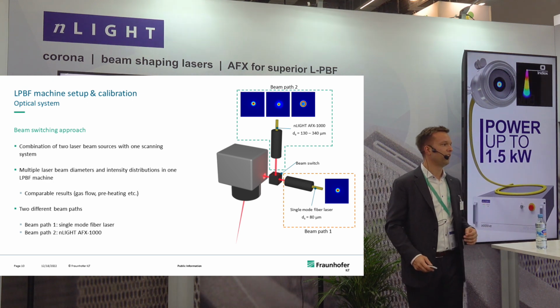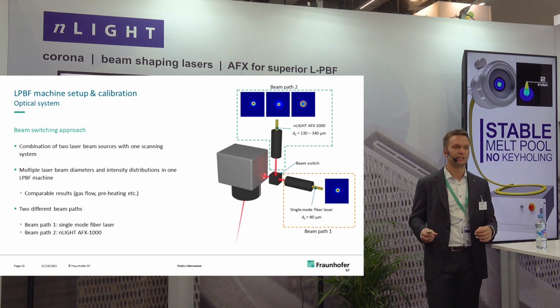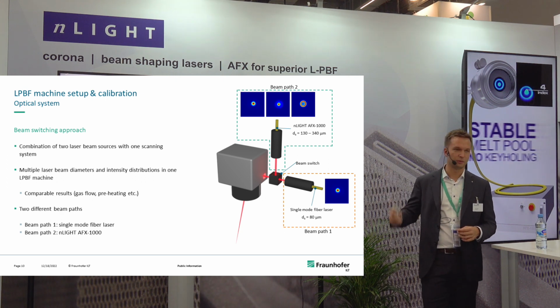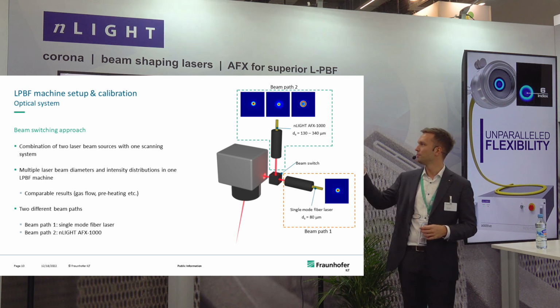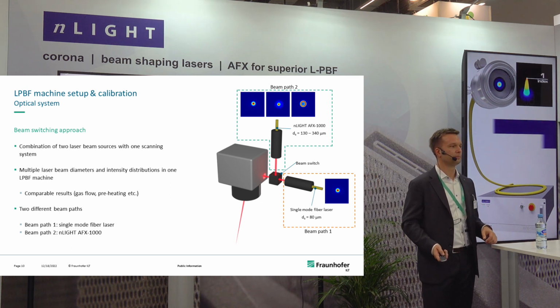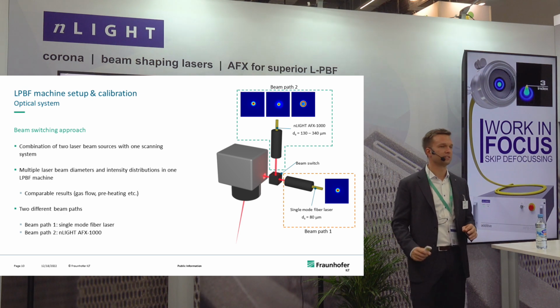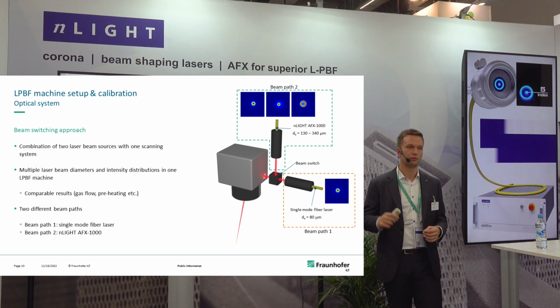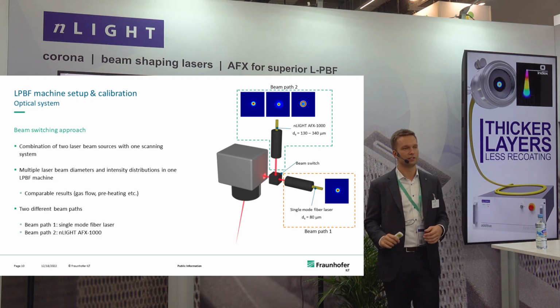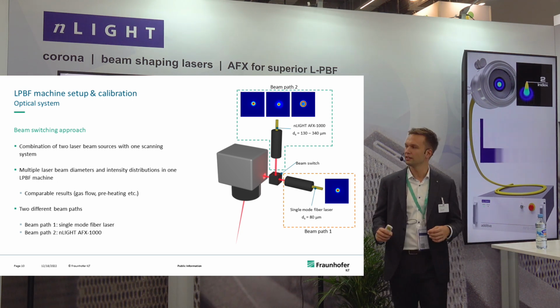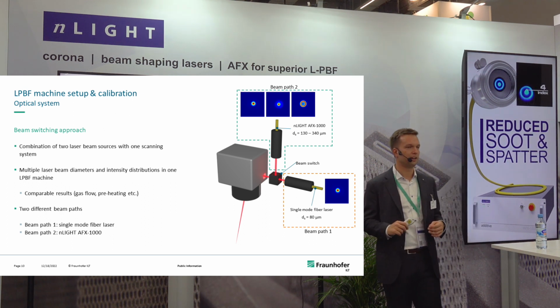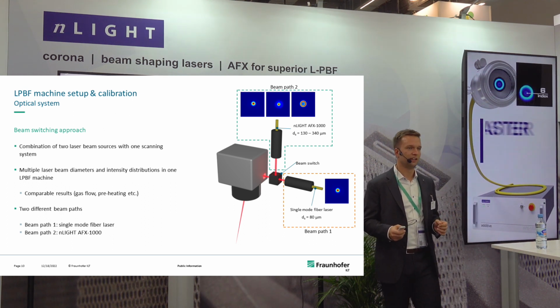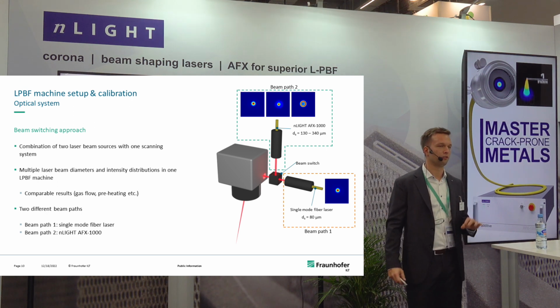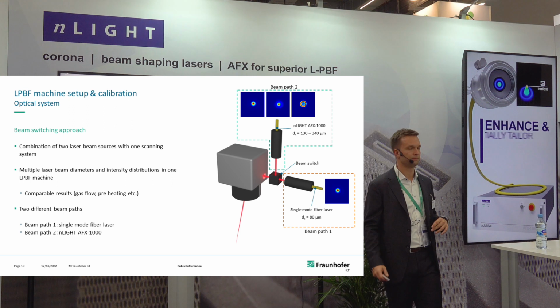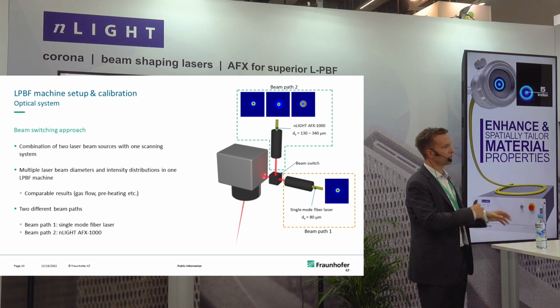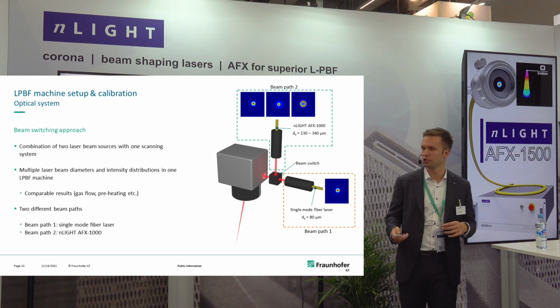As I mentioned already, we have a beam switching system in our machine that allows us to select one of two laser beam sources, one being our AFX laser, which yields beam diameters between 130 and 340 microns, depending on the AFX index setting we are using. And in our first beam path, we have a standard single mode fiber laser, which yields a beam diameter of around 75 to 80 microns. So more or less towards the state of the art as it is in most machines right now.